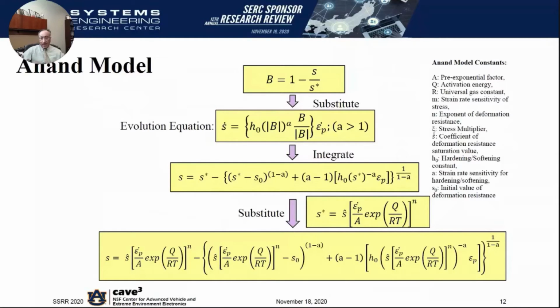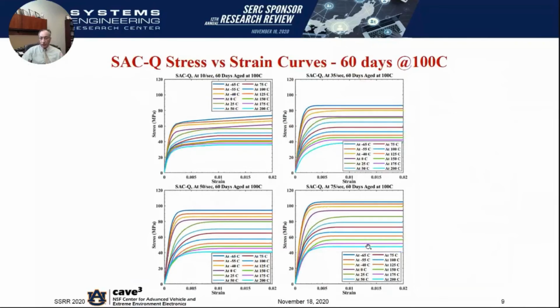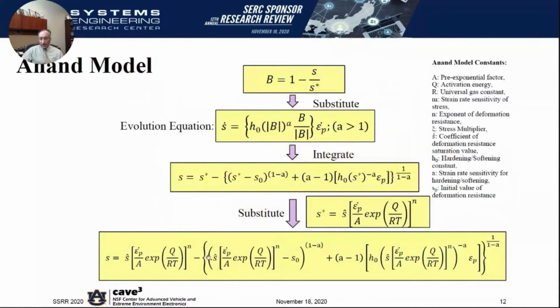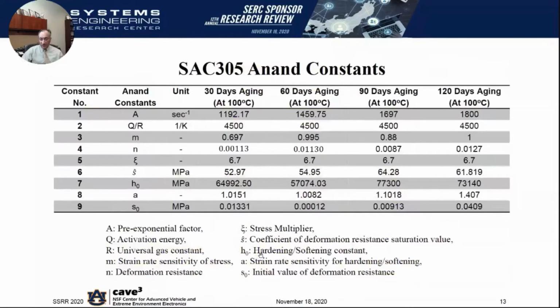The true package deformation behavior is a three-dimensional scenario where the material could be subjected to stresses and strains along all three orthogonal directions. So the way to capture the material behavior in this computational framework is to be able to fit this material law to the entire set of data that I was showing you earlier on. And the way one does that is by fitting the 9 constants that characterize this particular constitutive equation. And that's what we have done as a part of this exercise. So these are the 9 constants that represent the material behavior. And what we have done is we have fit these constants for each duration of thermal storage. So for 30 days, there's one set of constants, 60, 90, 120 days. So each set of constants represents one duration of thermal storage for the material in its end application.